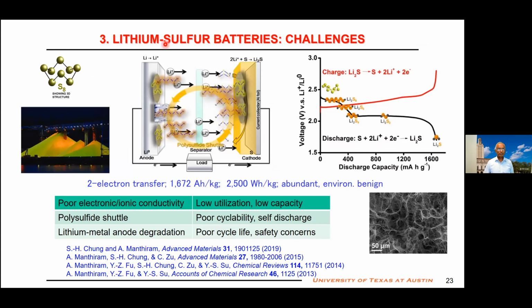No transition metal is involved here. The interest here is they have huge capacity, 10 times more than lithium cobalt oxide, because of 2 electron transfer, and sulfur is also lighter, there is nothing else present there. So you can get a huge amount of charge storage capacity with the sulfur, but it doesn't come easily. There are problems. Sulfur is a poor electronic conductor and a poor lithium ion conductor. So when you charge and discharge, the electron comes, the ion comes, they have to diffuse or move through easily. That is a problem. Low utilization.